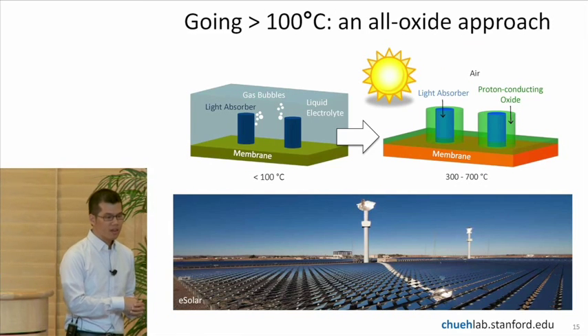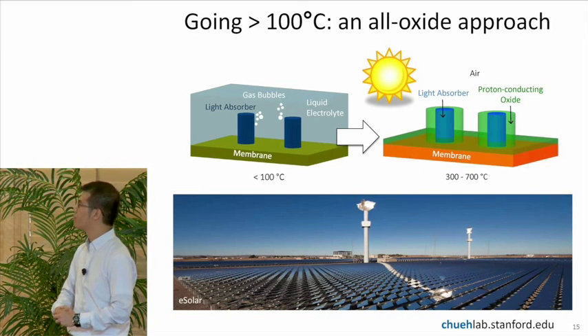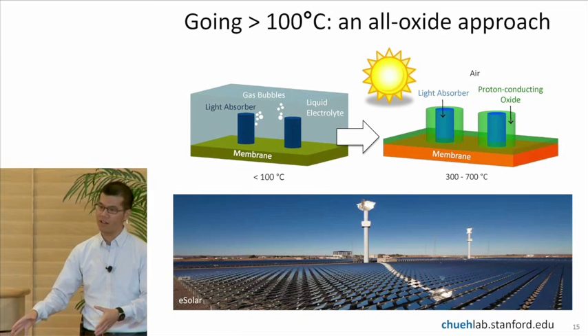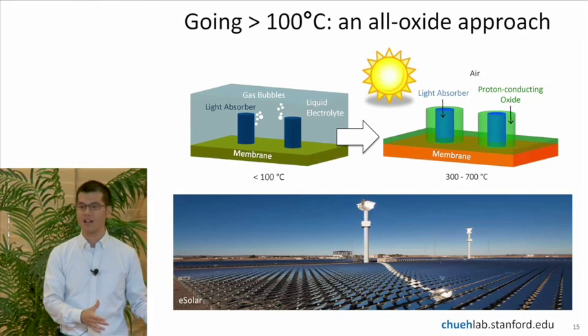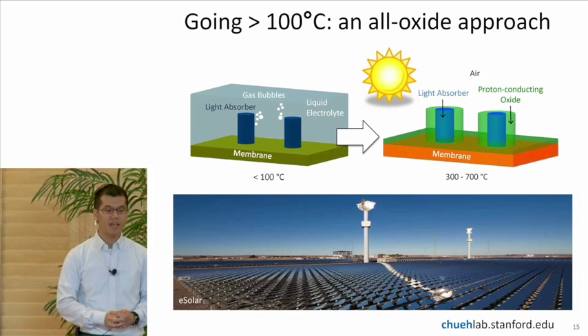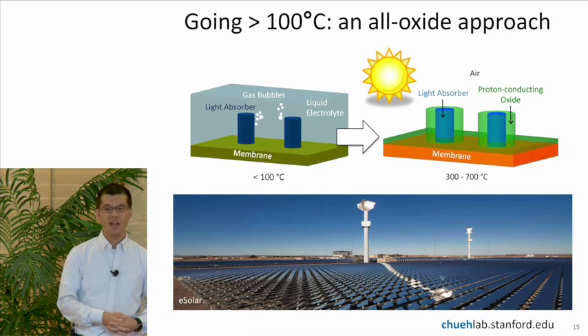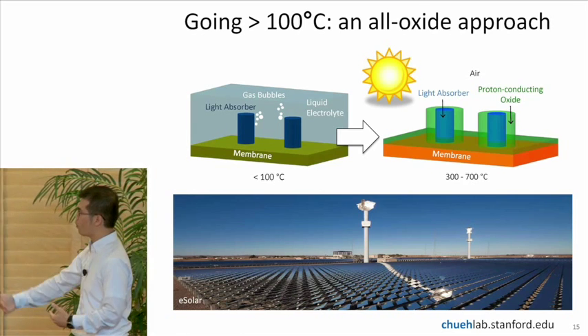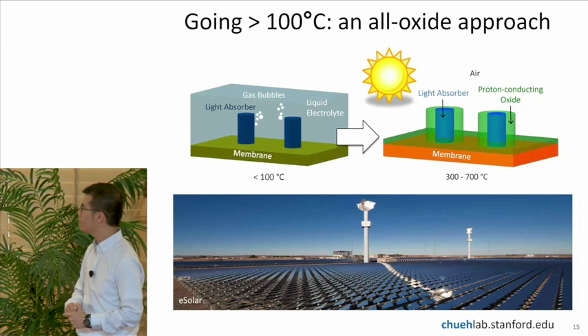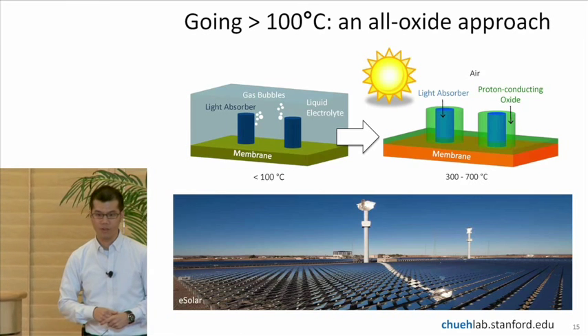So this is my last slide. All is great. We can go up to about 100 degrees C, but then water boils. Then we're out of luck. So actually, the main thrust of our GCEP work is to look at how to take the liquid cell up into a solid state cell in which the temperature can go far beyond 100 degrees Celsius. So we essentially take the liquid electrolyte and replace it with a solid electrolyte that can go much higher in temperature. These are typically ceramic materials. And then to achieve the type of temperature needed, say four or 500 degrees Celsius. This is where I showed the efficiency simulation to exhibit the highest value. We will need also some sort of solar concentration system as well. And I showed just a one possibility of using a heliostat field.